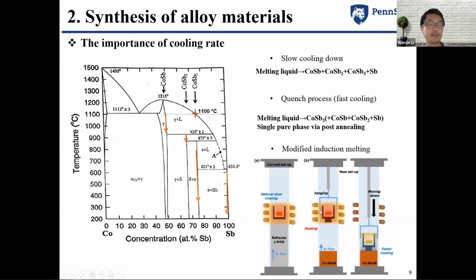And right after the heating is finished, we just lower it down and make it contact with the copper block at the bottom directly, where the copper block is cooled by the circulating water. So in that way, we can provide a faster cooling rate for the materials that we prepared by the induction melting. But still, the contact area between the crucible and this copper block is limited, so the cooling rate we can provide by even this method is still limited.